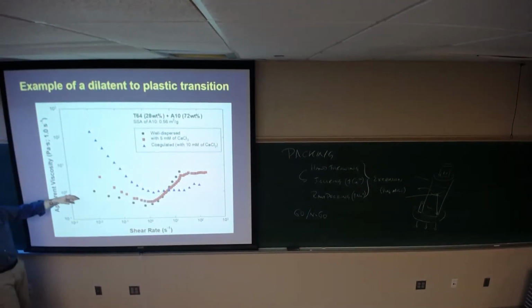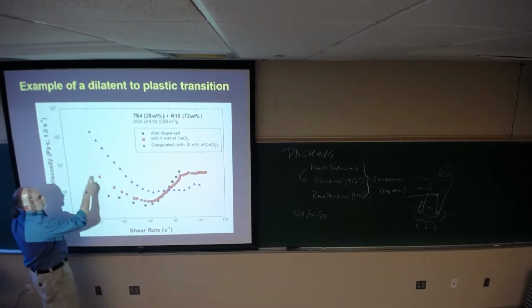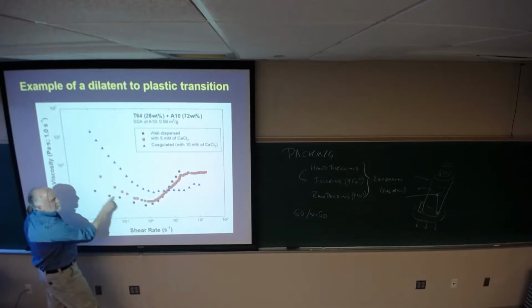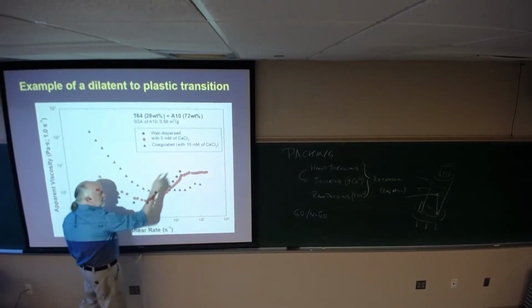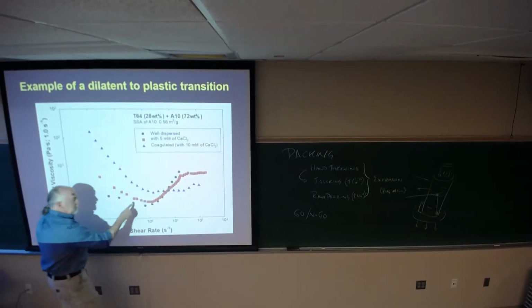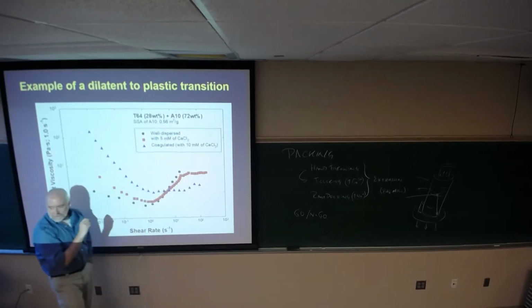we demonstrated this idea. This is viscosity versus shear rate. This is for a relatively high concentration suspension. The fact that we have two different particle sizes is not important. The fact is that I have a crowded system. So what I get here is while the dispersed system comes down, I get my shear thinning, and then at some critical shear rate, the viscosity goes back up. This increase in viscosity is dilatancy.